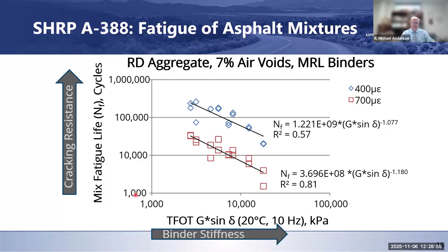In this case, fatigue life is on the y-axis. G star times sine delta is on the x-axis. This is after thin film oven aging, very similar to RTFO. And that's appropriate because the mixed specimens that were produced were after short-term aging. I think they were 4 hours at 135 C before they were compacted and then tested overall.